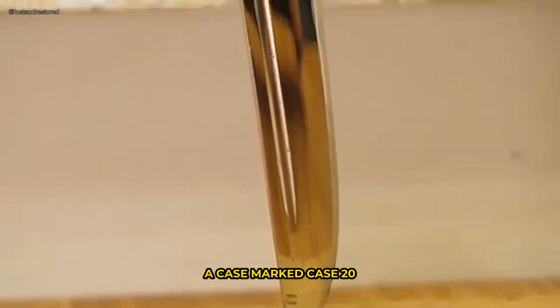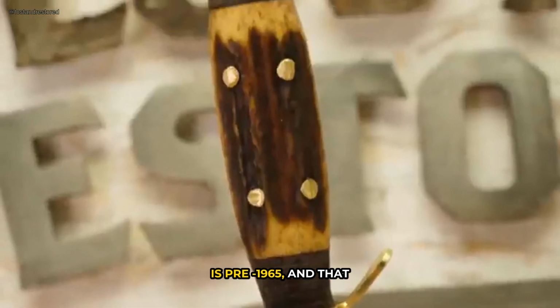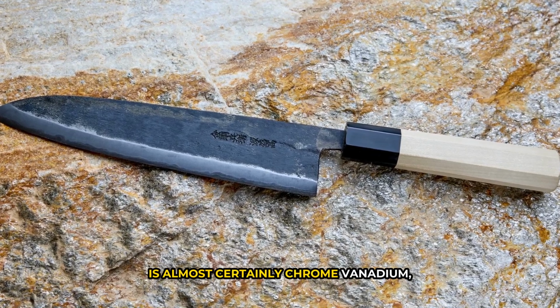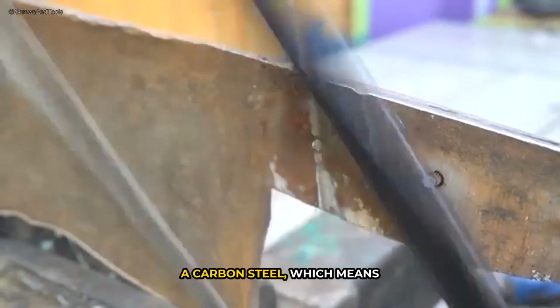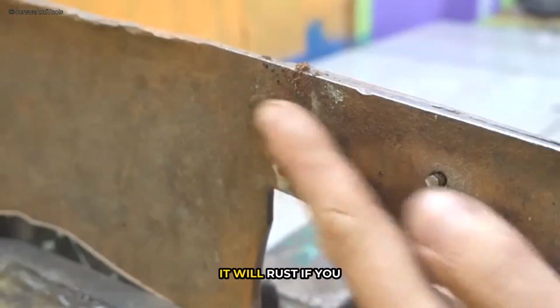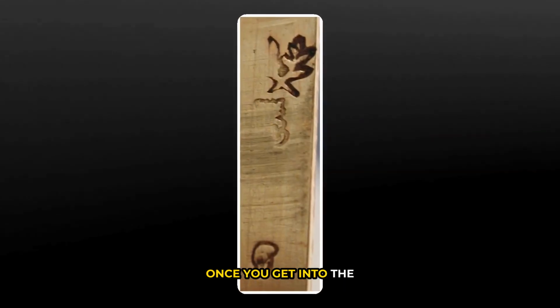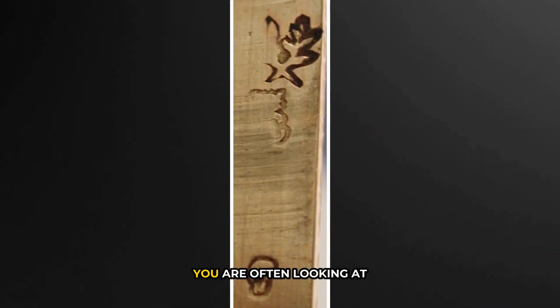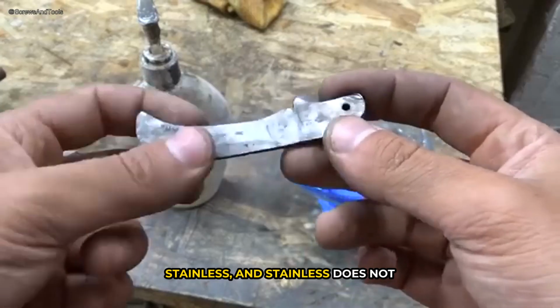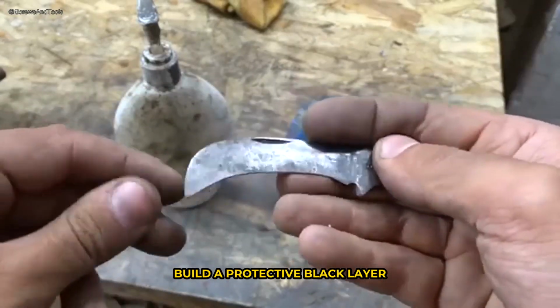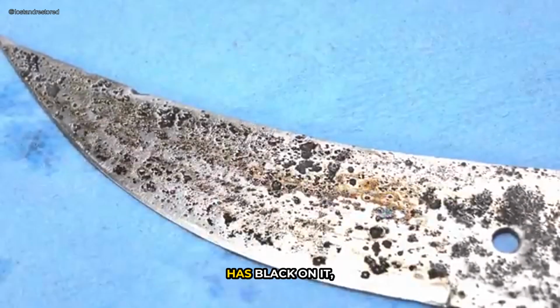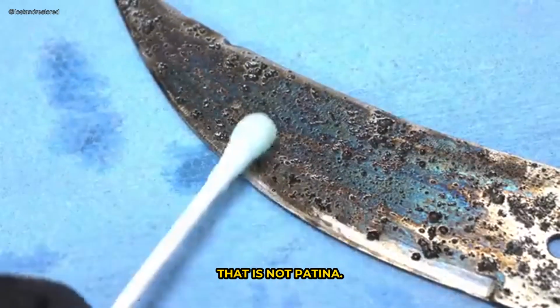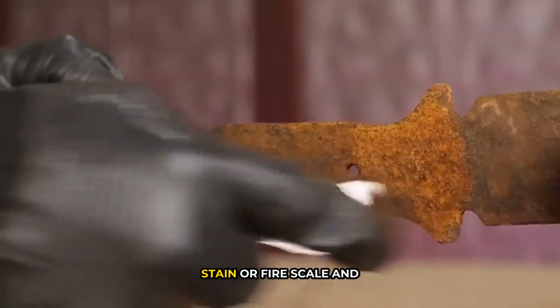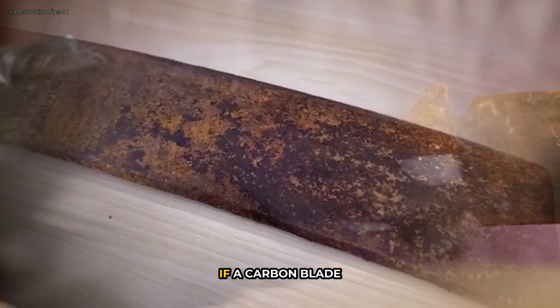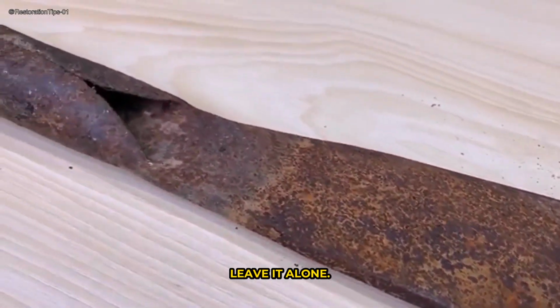A Case marked Case 20 with no USA under it is pre-1965, and that is almost certainly chrome vanadium, a carbon steel, which means it will take patina and it will rust if you let it. Once you get into the dotted stamps of the 1970s, you are often looking at True Sharp, a 420 series stainless, and stainless does not build a protective black layer at all. If a stainless blade has black on it, that is not patina. That is dirt or a stain or fire scale, and it comes off. If a carbon blade has black on it, leave it alone.